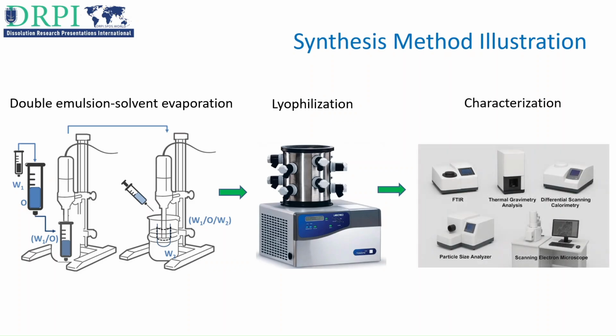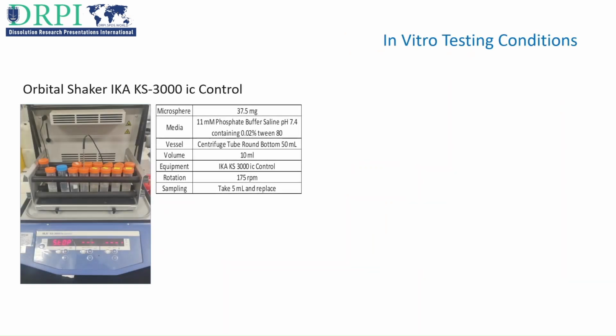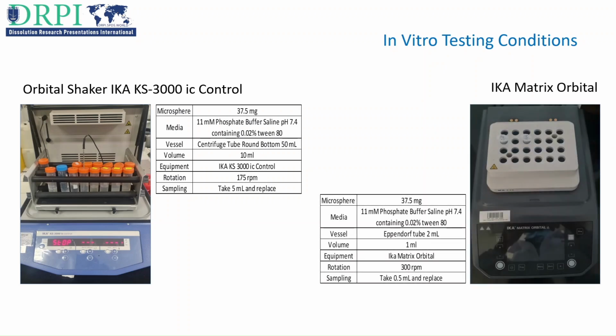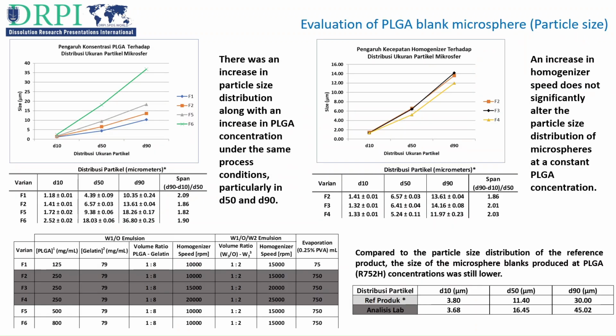The final microspheres were characterized using Fourier transform infrared spectroscopy, thermal gravimetric analysis, differential scanning calorimetry, particle size analyzer, and scanning electron microscope. In vitro dissolution testing in this research was performed under two different conditions. The first one is using an orbital shaker with 10 milliliters of medium at 175 rpm, and the second condition is using a matrix orbital with 1 milliliter of medium at 300 rpm.